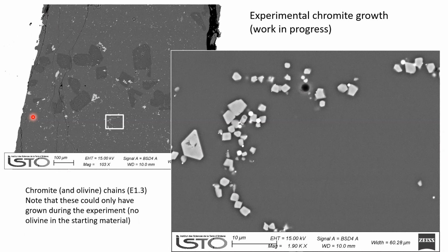I won't go into all of that, but I just want to show you one of a few experiments that we've done recently with Zoja here. This is an experiment taking a Hawaiian basalt, doping it with a bit of extra chromite and olivine, and cooking it up in air to about 1600 degrees. So all of the olivine and almost all of the chromite dissolves, and then we re-equilibrate it at a lower temperature. So we're growing chromite from a very significantly chromite supersaturated liquid. And what do we get? We get these little chains.